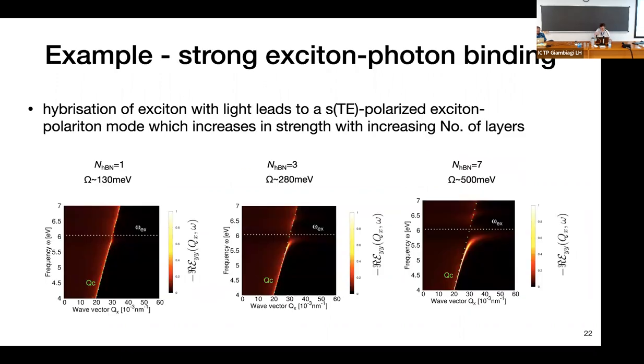When you solve the second part and obtain the hybrid modes by solving the Dyson's equation, you can see that for a single layer of HBN, the dispersion of light is almost unperturbed. This indicates also the dispersion of exciton, but where they cross there is a bit of a change. In a single layer HBN, obviously the hybridization between the exciton and photon is not strong, but if you make a bigger heterostructure and as you add layers, this coupling strength increases significantly and you see the photon line actually bending significantly. So you really get a very strong hybrid exciton-polaritonic modes. This allows you to calculate these kinds of properties for many different combinations of Van der Waals heterostructures.